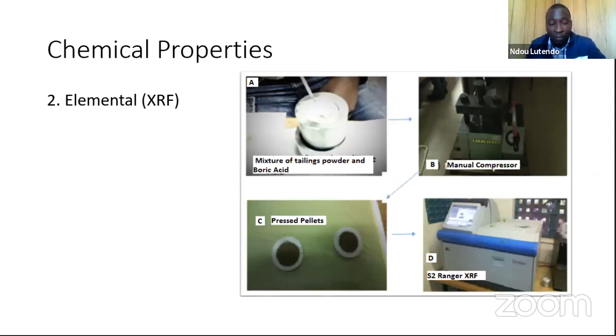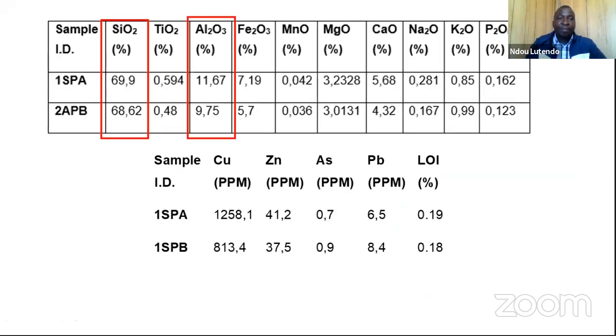Now, with elements, as I indicated, I used XRF. And with XRF, this is just basically the method. You mix your tailings powder with boric acid. Boric acid is a binder, actually. It binds your pellets, as you can see, so that they can be put inside an XRF machine. And inside the XRF machine, this is where you're gonna get your results. And here are my results.